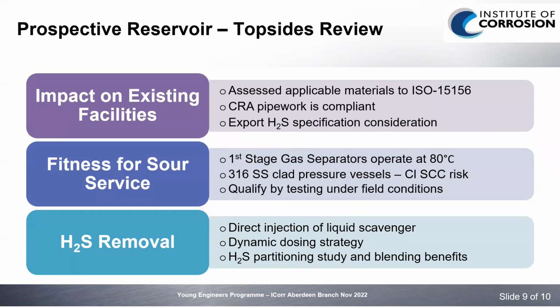Where a problem did arise was the first stage gas separators, which operate above the typical threshold for stress corrosion cracking at 80 degrees temperature wise. They're also 316 stainless clad. So the chloride stress corrosion cracking risk is quite high for these.